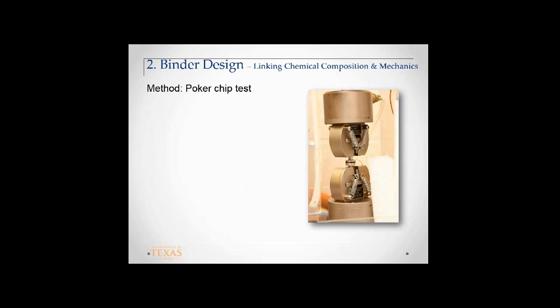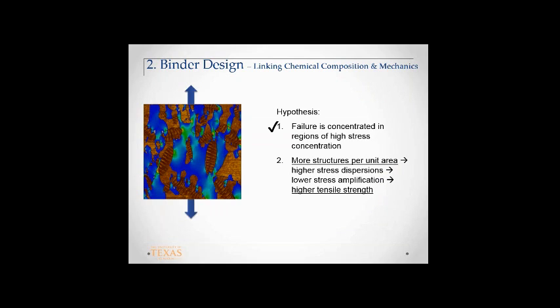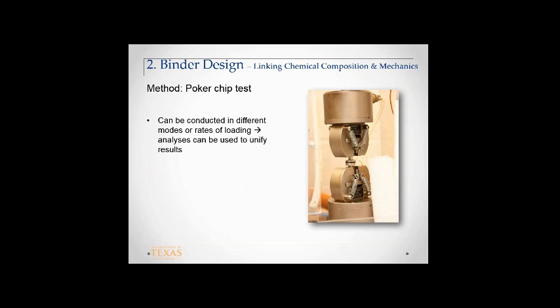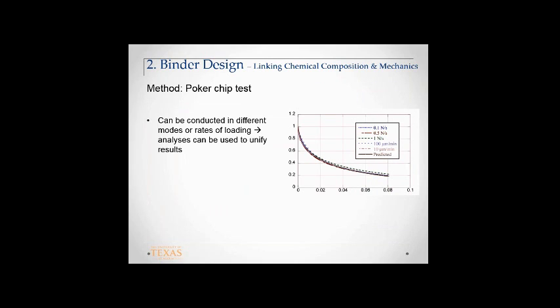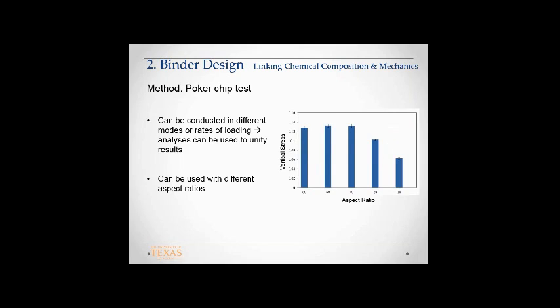The second hypothesis was that with these structures you get less stress amplification, more dispersion, and therefore higher tensile strength. So we tried this with the poker chip test. Now, the poker chip test is, like I said, the sandwich-based test. You can conduct this test in load control or displacement control mode and unify the results. On the x-axis you have a damage parameter, and here you have stiffness. You have results from three different loading rates and two different displacement rates, and you can see the damage behavior is uniform. So it's a material test independent of the mode of testing, and it's also very repeatable.